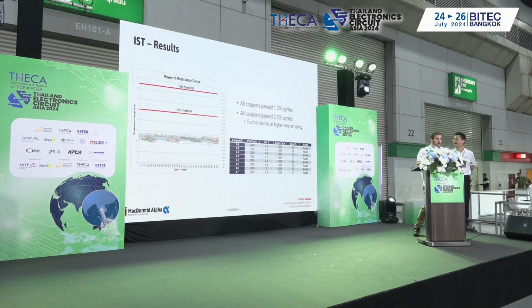We're continuing a second round of testing. We're processing more boards to run at higher temperature to push these conditions further so we can try and get a difference between these. But from the initial results, you can see that there's no reliability difference between the various processes, which means you can then go back and look at whether you're going to get savings or efficiency benefits in another step.